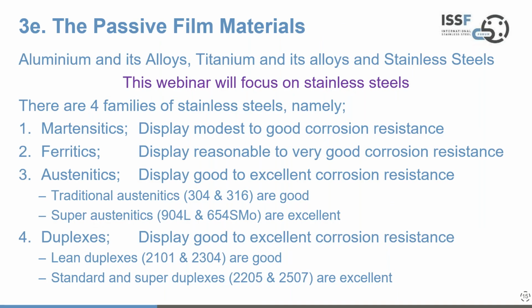So let's think about the passive film materials. We've touched on them already, and unsurprisingly, given that we're a stainless steels organisation, we're going to focus on stainless steels for the rest of the session. In the family of stainless steels, you've got four family groups. The martensitic group, which display modest to good corrosion resistance at the lower end of our spectrum. The ferritic group, which display reasonable to very good corrosion resistance. The austenitic group, which many people are familiar with, display good to excellent corrosion resistance, and you've generally got the 18-8, the 304, and then the moly bearing version of that, 316, which have good corrosion resistance, and moving into the super austenitics, 904L and 654 SMO, have excellent corrosion resistance.